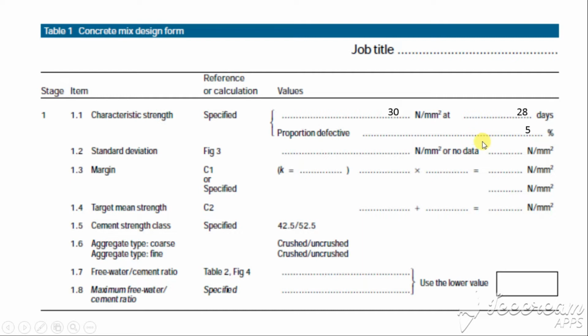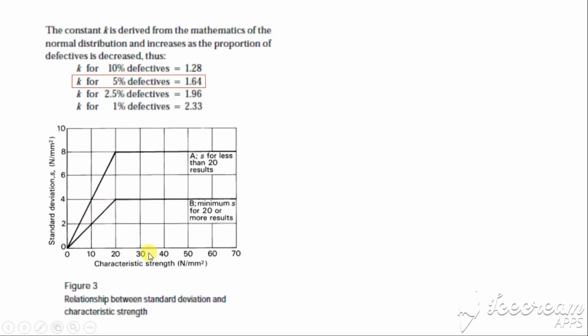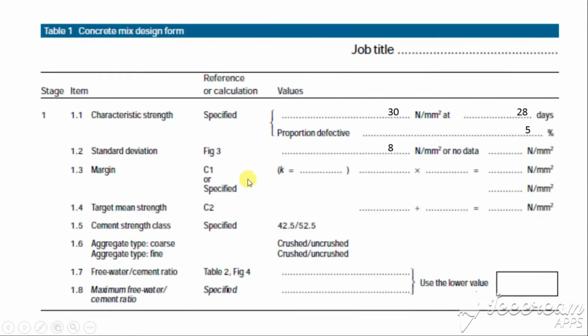for proportion defective 5%. For the standard deviation, we will refer to figure 3. Okay, this is figure 3. 30 MPa, we project to line A and we will get 8 Newton per mm square here. For the margin, refer to the C1 formula. We will get K equal to 1.64, and then the value of K will multiply with 8 and we will get 13.12, and then you need to round it to the nearest, so you will get 13 here.